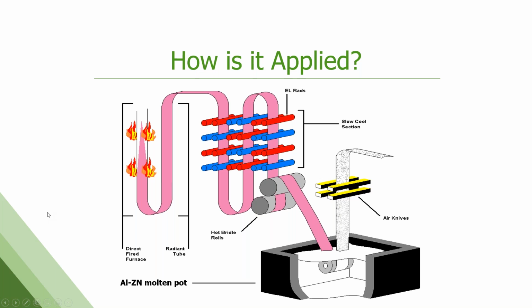This is a little bit closer up of the meat of the line, I like to call it. This is where the action is happening. So you've got the direct fire furnace, the flame in there, and this is anywhere from 1,000 to 1,500 degrees that you're heating the strip up to. It goes through these radiant tubes and these hot bridles to get further annealed, get the structural properties that you need. And then through the bath, there's a roll that sits down in this molten pot of metal that the strip runs along. It comes up, you've got your air knives there that are controlling your coating weight, and then off to the exit of the line.